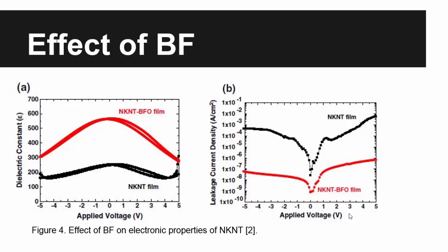On figure A, you see a much higher dielectric constant in the bismuth ferrite doped NKNT film compared with the non-doped material. Likewise, there was a much lower leakage current density in the bismuth ferrite doped film.